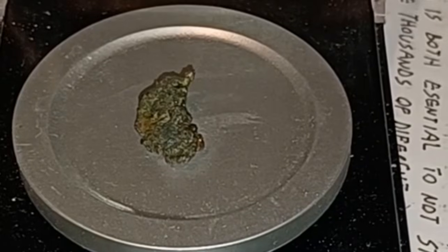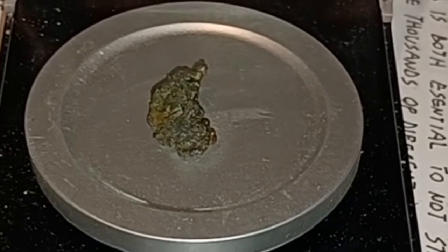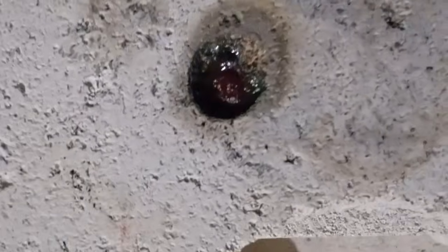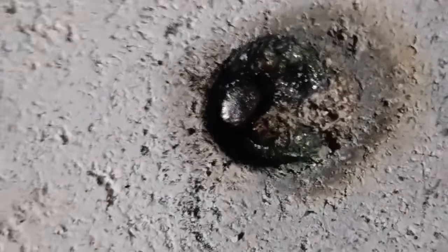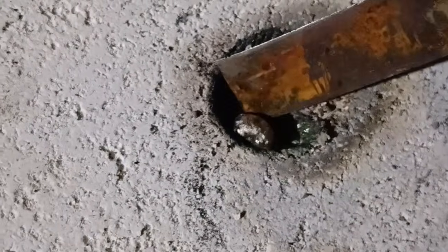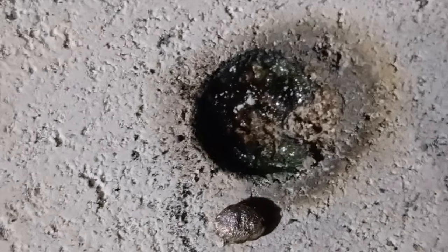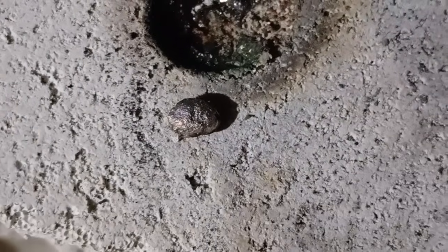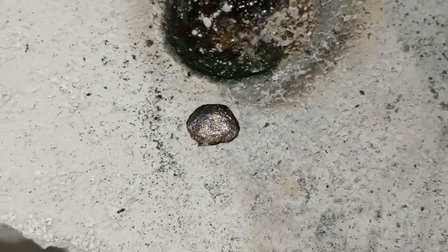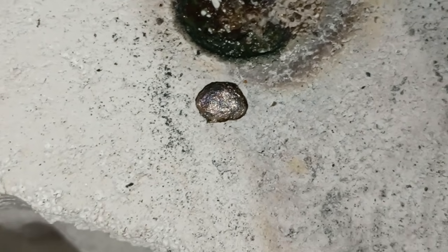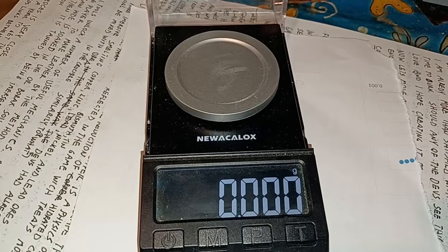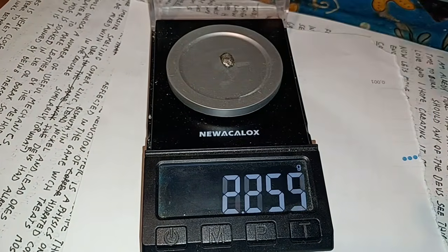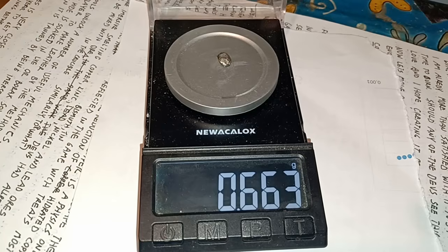so I removed it from the crucible, placed it on a found brick, and directly heated it with the arc. It melted in a few seconds. I failed to record this particular bit because, apparently, thick leather gloves and touchscreens don't mix. Anyways, I got 0.663 grams of what looks like palladium.